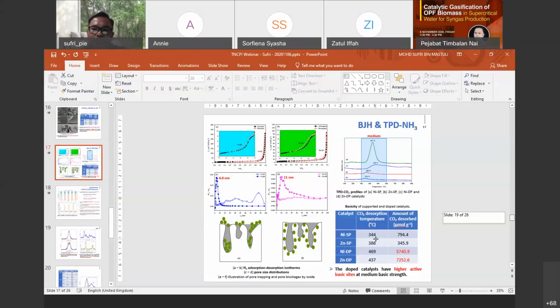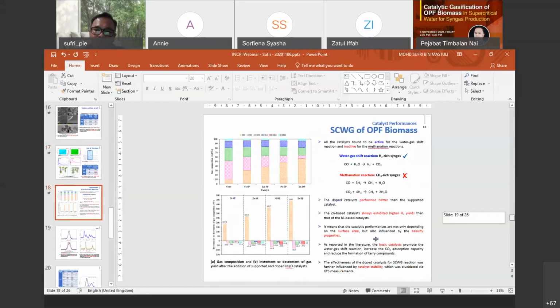So how do I relate the basicity to the catalytic performance? According to the literature, as I mentioned just now, to promote the water-gas shift reaction, we need a basic catalyst. It's not an acidic catalyst. If it is an acidic catalyst, the water-gas shift reaction is not activated. So the basic catalyst will promote the water-gas shift reaction. It provides the reaction medium for the carbon monoxide to react with the water, in order to boost and elevate the yield of the hydrogen.